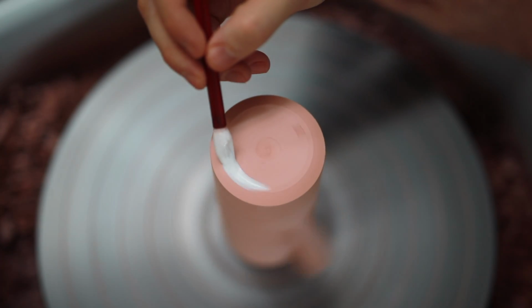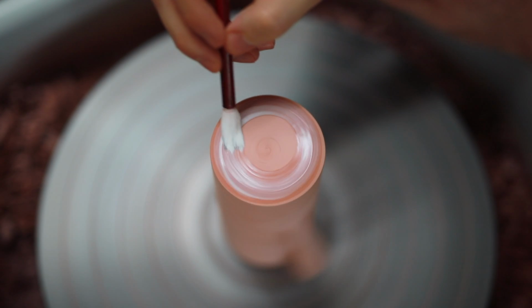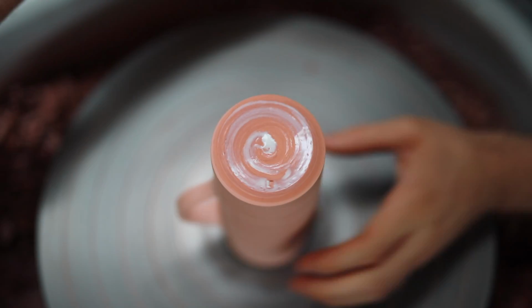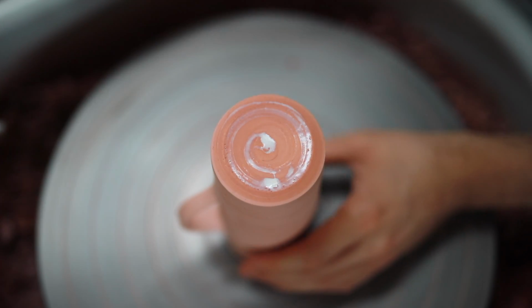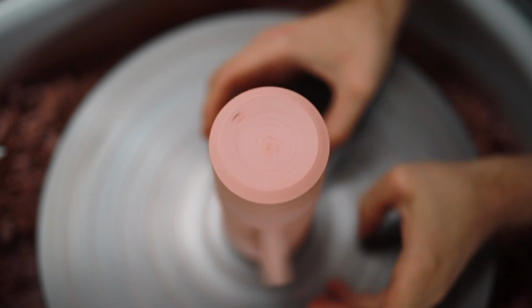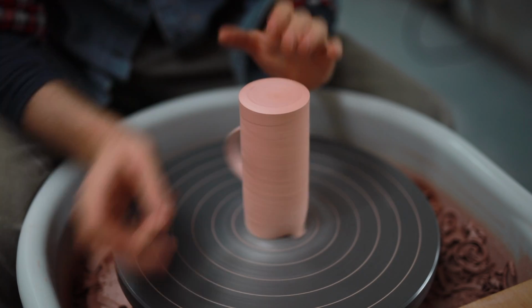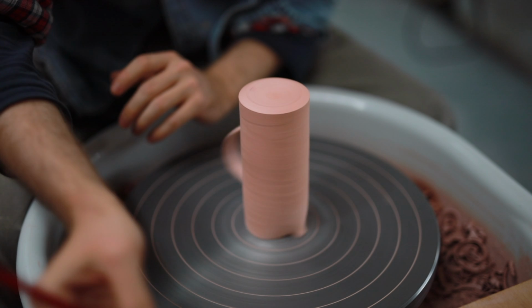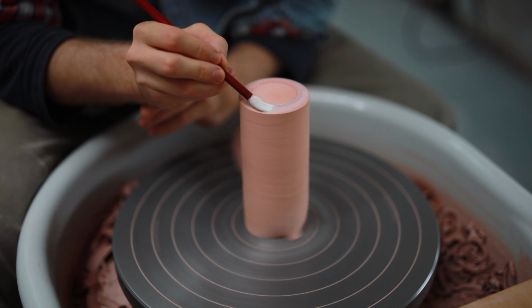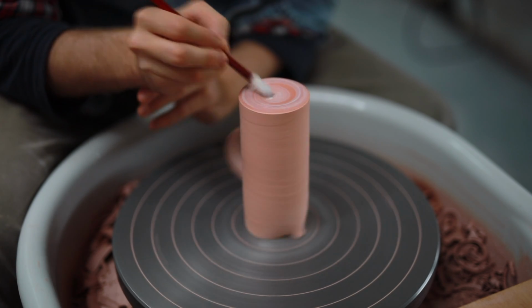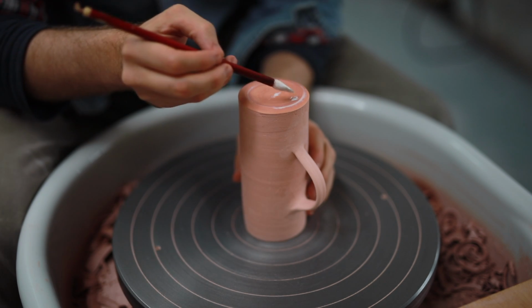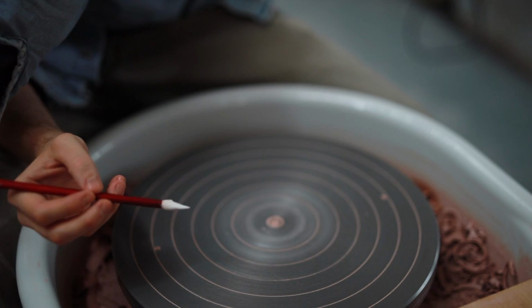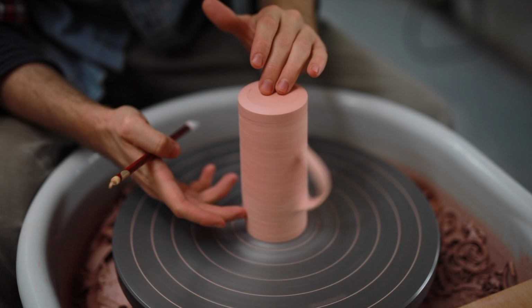The next step is to apply wax onto the bases, which acts as a simple resist for when I'm glazing. You'll see that I dab a little bit extra just where my maker's mark is, as cleaning glaze out of that little notch can be very tricky. The jugs at this stage are still fragile, but not nearly as much as when they were bone dry, especially as mine are made very thinly. If I were to squeeze the rim too hard, they'd still crack and split at this stage.